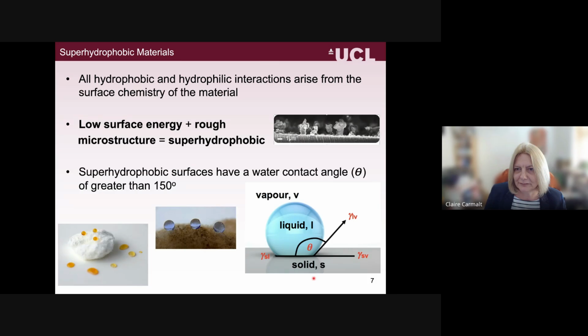So as well as hydrophobic, we've also looked at super hydrophobic. So if I could just introduce that to you. So obviously all hydrophobic and hydrophilic interactions really arise due to the surface chemistry of the material. If you're looking to go from hydrophobic to super hydrophobic, what you have to have is quite a rough nano or microstructure. And this gives you an example of a super hydrophobic film we deposited. I'll talk about those in a moment. And this is just a side-on SEM. You can see how rough the morphology is.